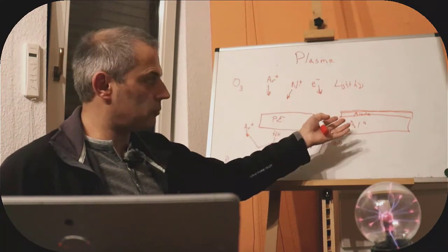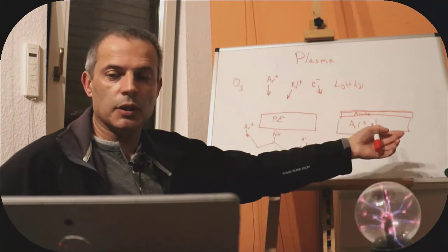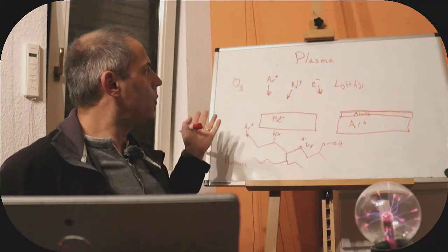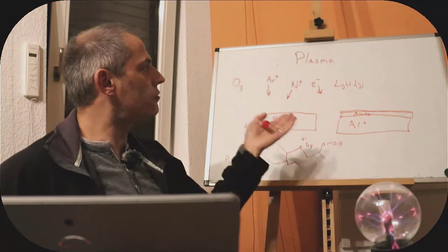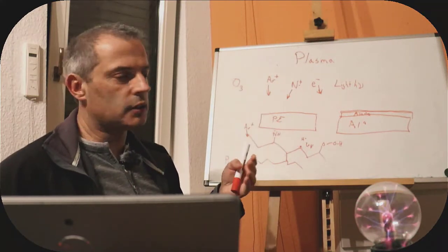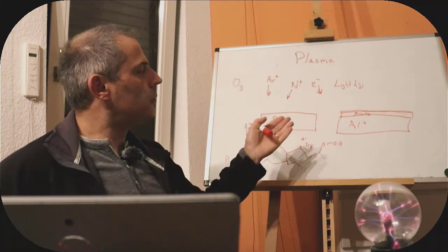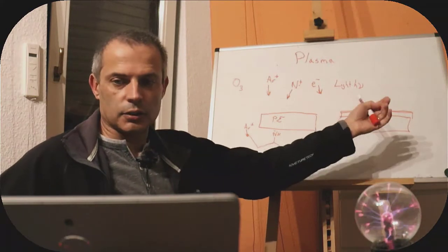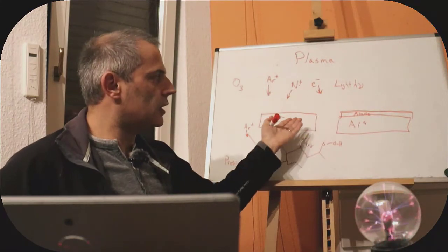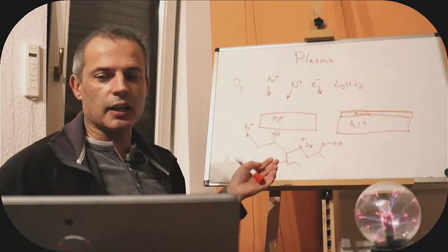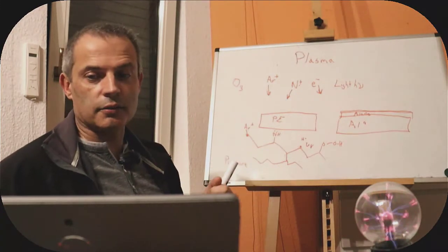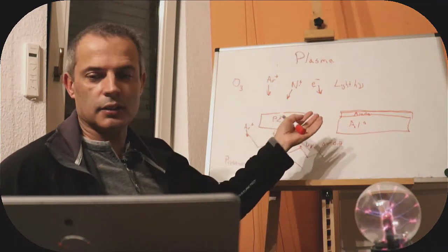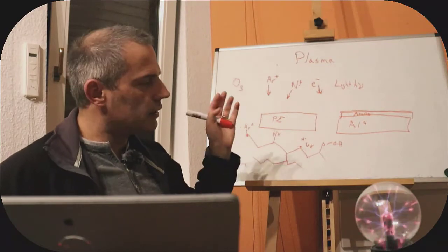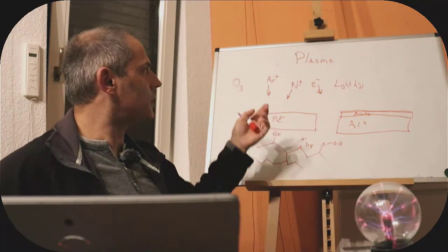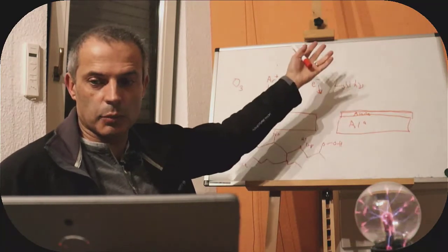So if we want, for example, a clean aluminium surface with no aluminium oxide on it, we can take it off by shooting it off with argon ions. We do have to be a bit careful, because it causes a lot of damage to the crystals. So you can't just generate a perfect flat aluminium surface with that. You then have to post-treat it in some way to get back, typically by annealing, to heal out all of the problems that you've done and any argon that's inside to let it back out again.